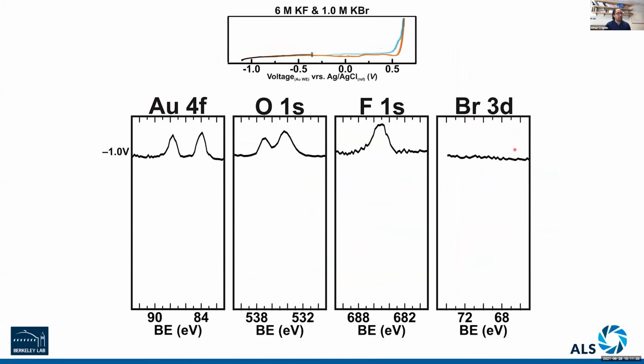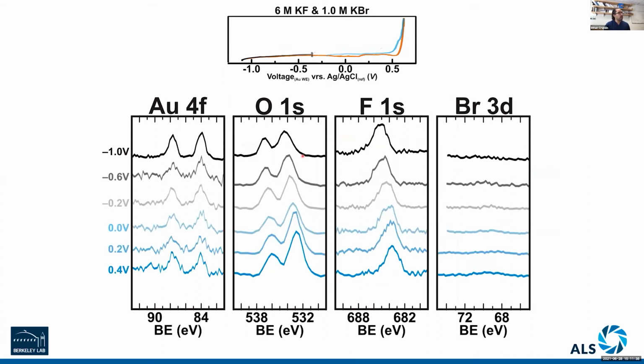We're going to collect everything the same way. We'll even collect the bromide. Even in this case, the sensitivity is not so high, even with 1 molar in there, but we'll collect it anyways. Again, all the same properties essentially happening with potential control as we're going up, and now we're just before something active happens. When we get to something active, where we get to the 0.6, we see dramatic changes to the spectra that's taking place. So now you can see very clearly how we're learning something about the interface at the solid liquid interface simultaneously with this driving. So the bromide comes really flat out in a very clear way, and we see multiple chemistries of the gold.